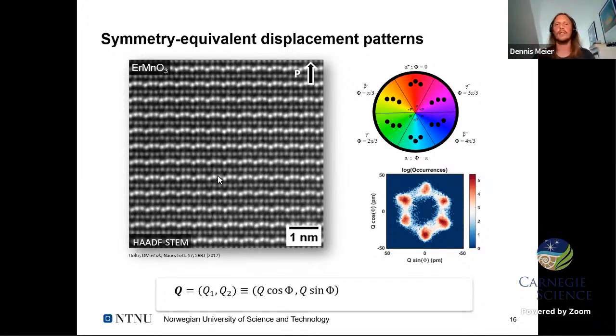Actually, you can change this modulation by 60 degrees, which is illustrated on the right hand side here. And all these modulations have the same energy. So we do not just have this up, up, down. We can also have up, down, down, up, down, up, and so on. So all these states are energetically equivalent. And you can also see that in this nice data set from Megan and Julia. All 6 states are populated.